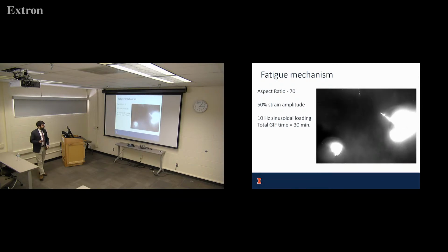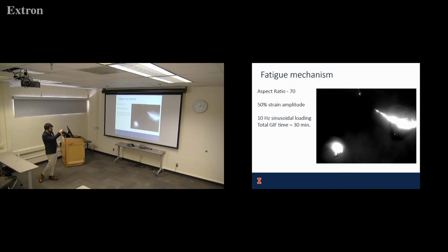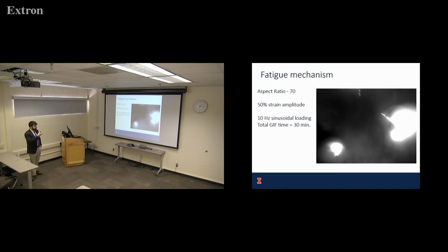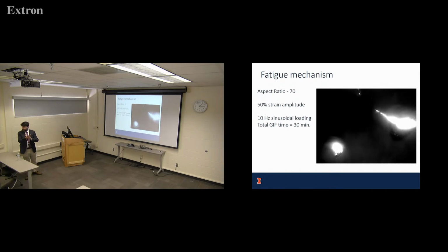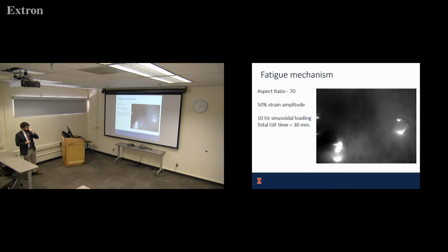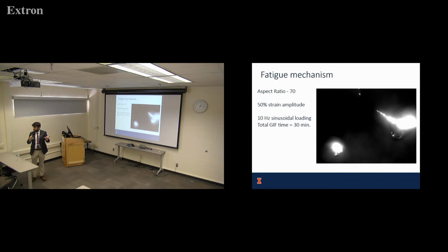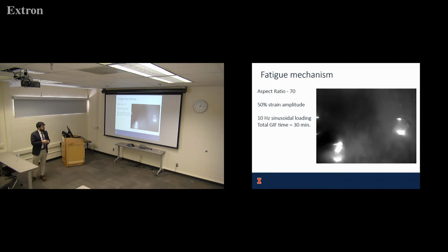Yeah, actually this was a big question for us too, and we're not quite sure, but you can see that illumination starts to go. I think part of it is the microstructures moving away from the cavity. In those first few cycles, those microstructures don't move yet, so they become exposed and heavily illuminated based on the damage. But a lot of that illumination is also from the bottom plate. The way that dark field works, if there's something scattering brighter, it will focus on that instead. That's due to the movement of the microstructure? Sorry? The movement induces that illumination?